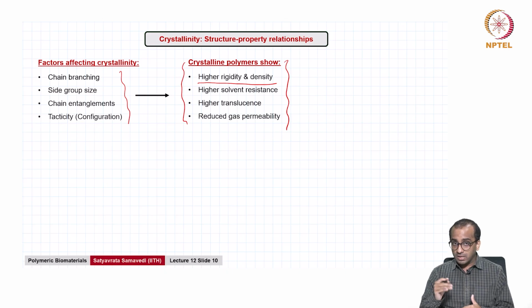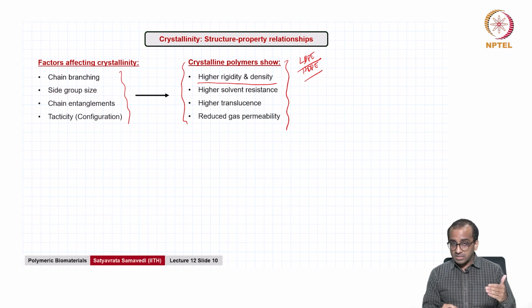If you remember, in an earlier lecture we talked about LDPE and HDPE, and the difference we saw was one of density, low density versus high density. You can now go back and ask, can I use my understanding of microstructure and crystallinity to help explain why one is low density and one is high density? The answer lies in how one of the polymer chains has a lot of long chain branches and the other has minimal or very small branches, affecting how the chains can pack.